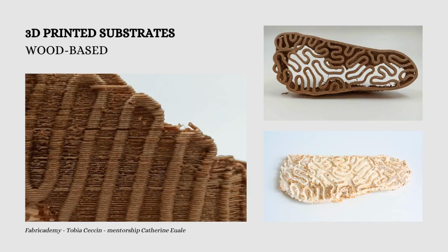And basically, it's held with a sugar, like a glucose binder. And once you extrude it, and you use a regular 3D printer for this, I should mention. So there are instructions. Once you buy this filament, you should follow the instructions to be able to print this well. Because what tends to happen with these biofilaments that are made for regular 3D printers, like there are also algae ones like Algix, they tend to be quite tacky. And so your nozzle might clog. And we have definitely had this happen and had to replace the whole nozzle.